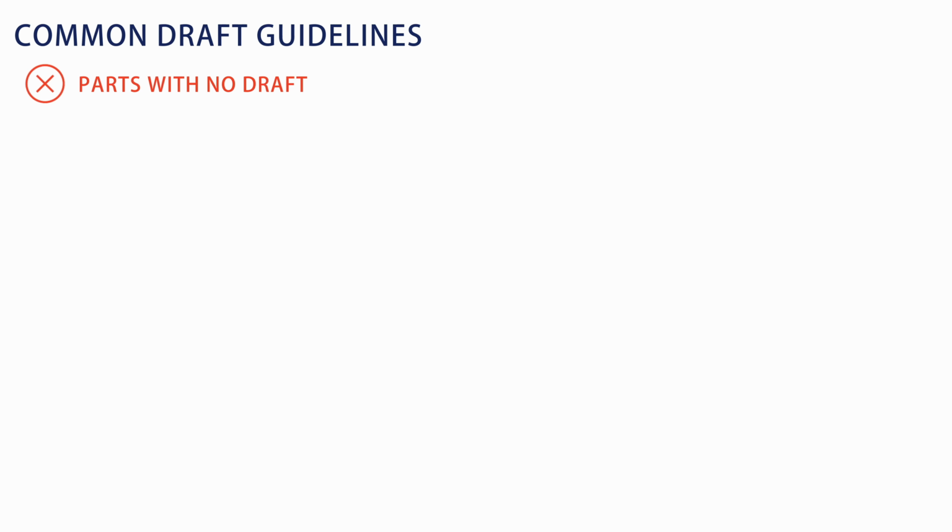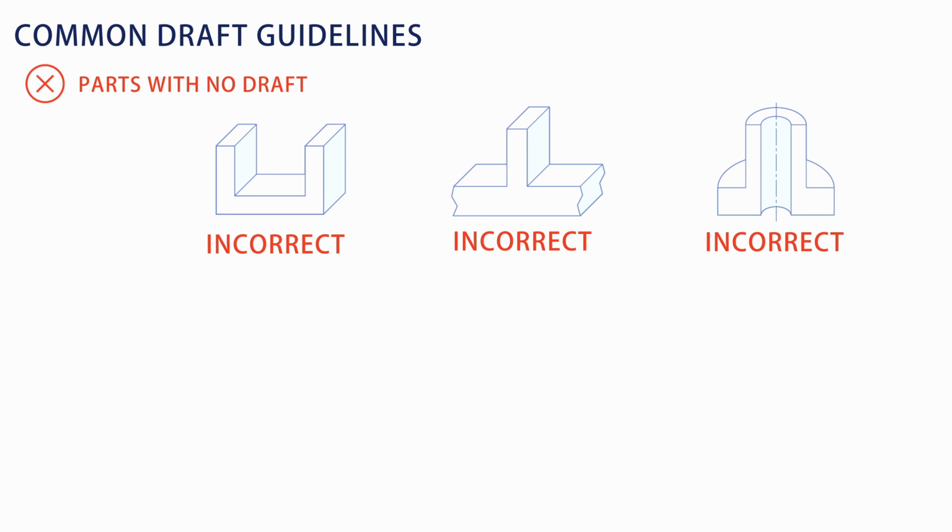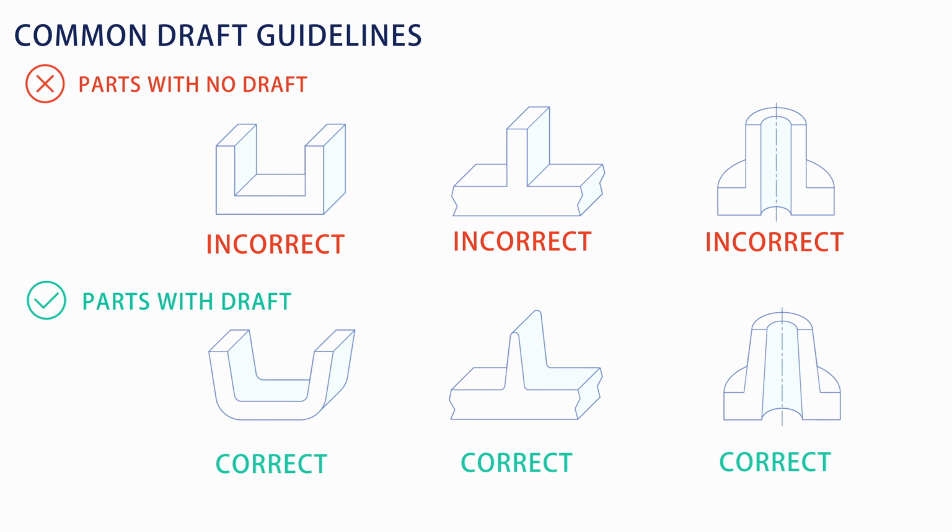Shrinkage as the molten plastic cools can cause the part to stick to the mold. Drafts allow for easier part removal, and drag marks are typical cosmetic defects if we don't add enough draft to the part. Typically, 1 to 2 degrees of draft per side is acceptable. For more texture, 3 to 5 degrees per side, and 5 degrees or more per side for heavier texture.